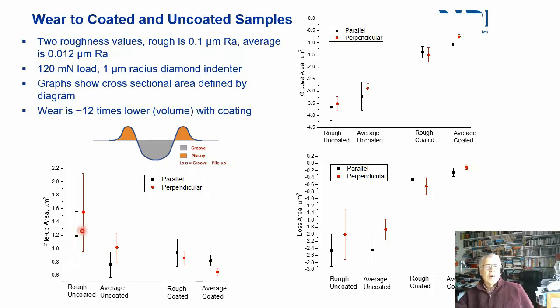uncoated example, and rather similar for all the other three examples. More interestingly, the groove area decreases, sorry, it's a negative figure, as the sample becomes coated. And here, by the way, we've got two roughness values, the rough example that you've seen already and also an average material, and I haven't shown any micrographs of this one.